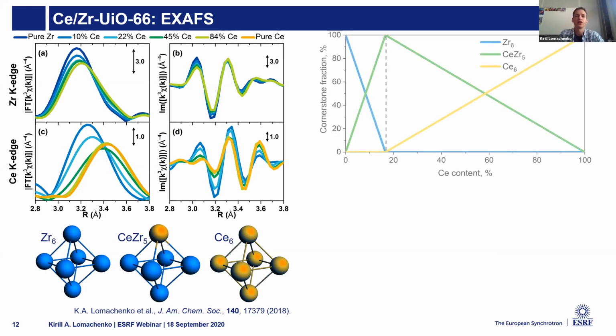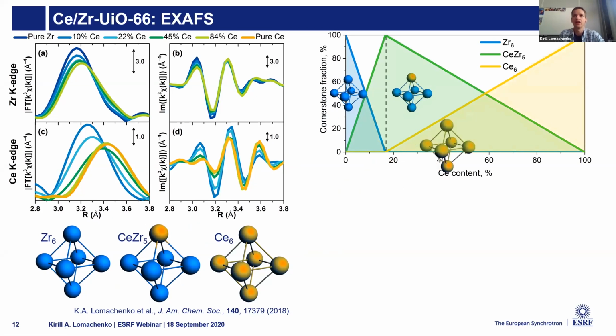And the latter should form preferentially at all the cerium contents, while the other two should complement the mixed metal cornerstone to reach the desired global cerium content. So this is a qualitative hypothesis that corresponds pretty much to what we see, but the good thing is that we can do an EXAFS fitting at the two edges for 6 different compounds at the same time.